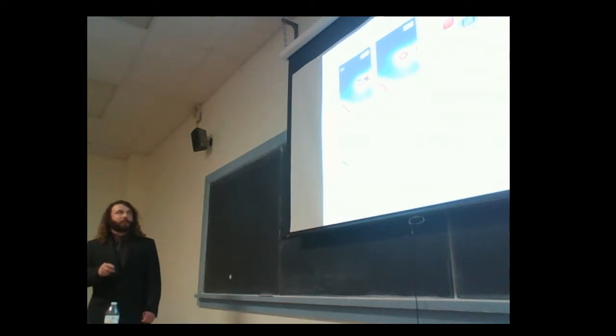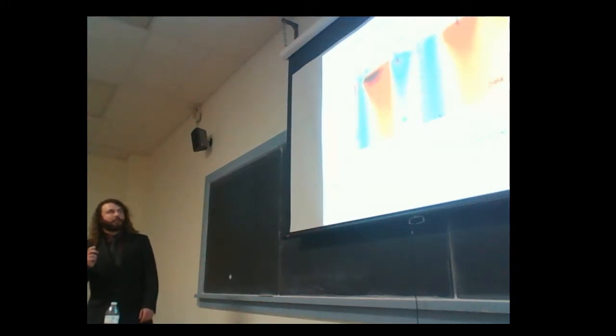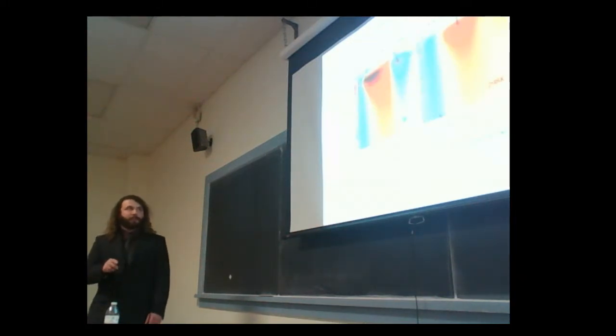Now, this is done with a transient ARPES measurement, but my measurements are transient optical, so what I actually monitor is the resonances between these electronic bands. So if they're monitoring this directly, I'm monitoring it through this 500 nanometer probe pulse right here. And this part of the band structure I'm monitoring through the 620 nanometer pulse. And so that gives you context for what these pictures look like.